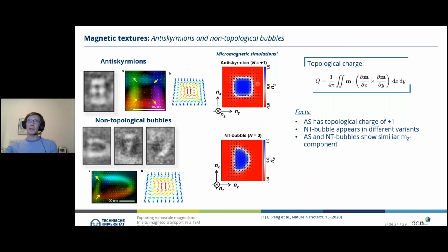Well, first thing what we can do is we can calculate the so-called topological charge. That is done by this equation here. So it needs to take the magnetization at one point and then the cross product of the derivative with respect to x and y. So this gives you, with the integration over the whole object, a quantity of how often the magnetization can be wrapped up onto a unit sphere. So for that object, the anti-skyrmion, that ends up equal to 1. And for the non-topological bubble, that's why it's called non-topological, if we apply this equation, it will not have a topological charge, topological winding number, however you want to call it.